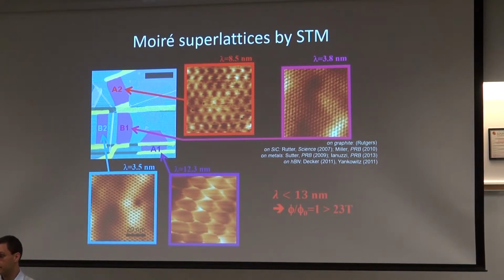So you make the two separately and bring them together. The graphene is not deposited on the boron nitride. We deposit it by hand. We pick up a sheet of graphene, we have a sheet of boron nitride, and we put it on top, one on the other. We don't know the lattice orientations exactly beforehand. We know them maybe modulo 30 degrees. But then if you just heat the whole thing, if you're off by a couple of degrees, it'll tend to want to align, because that's just structurally lower energy.